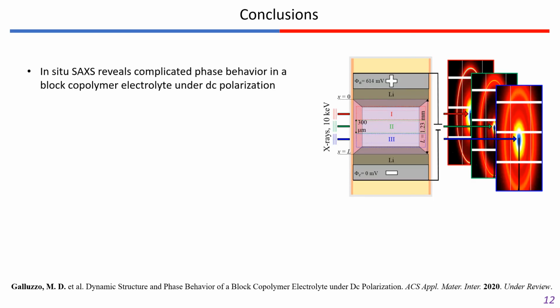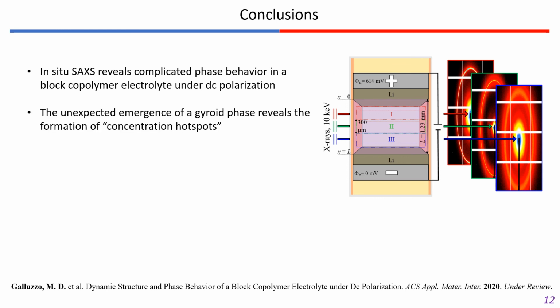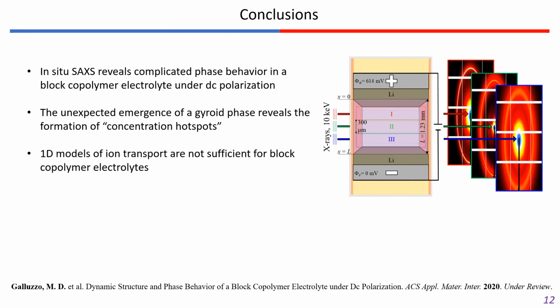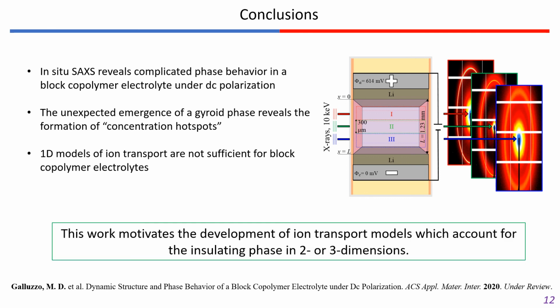So I'd like to conclude my talk with a brief summary. We've shown that in situ small angle X-ray scattering experiments reveal complicated phase behavior in a block copolymer electrolyte when we apply an electric field. We unexpectedly observe pockets of gyroid phase, and we attribute this to the formation of concentration hotspots due to the 3D structure of the block copolymer electrolyte. And what this tells us is that 1D models of ion transport are not sufficient for block copolymer electrolytes, and this work motivates the development of ion transport models which can account for the insulating phase in 2 or 3 dimensions.